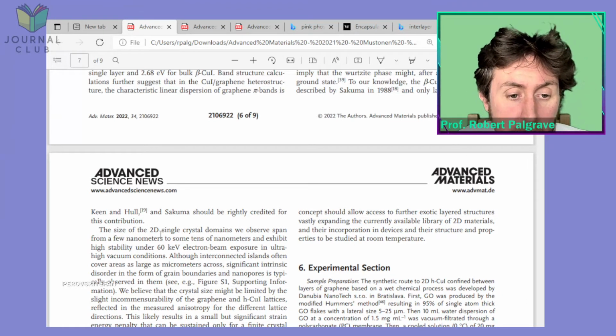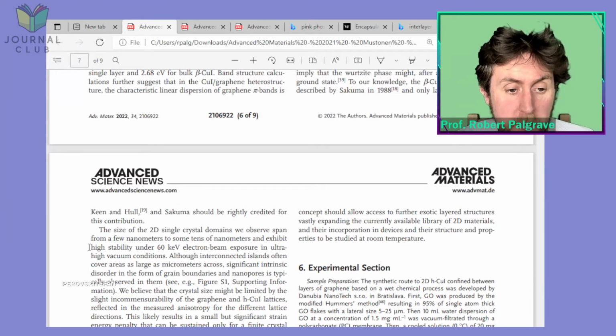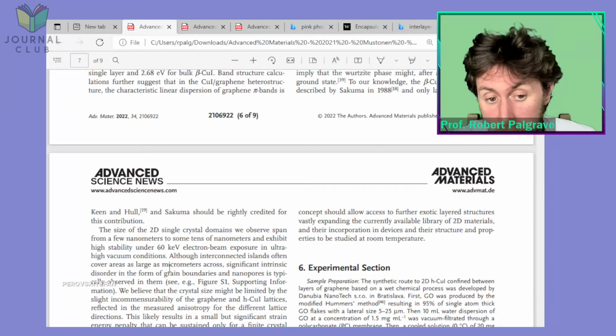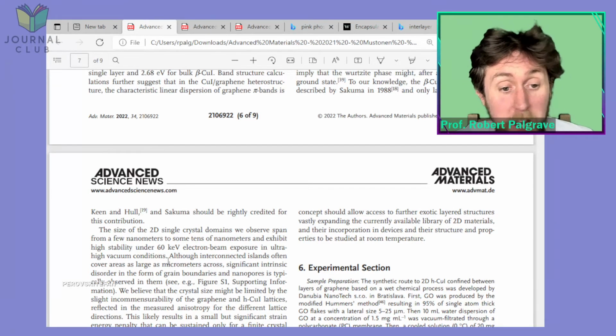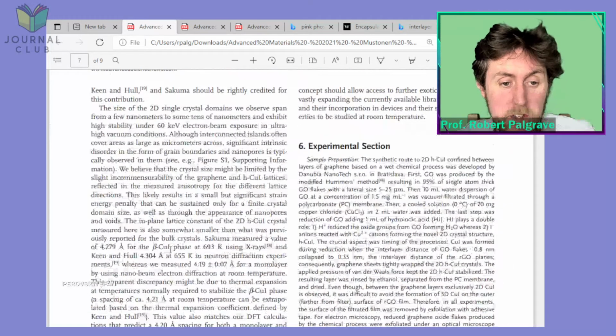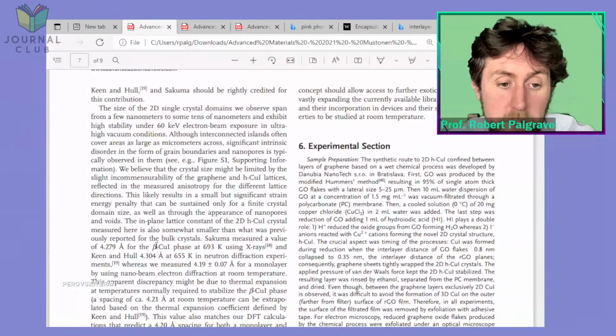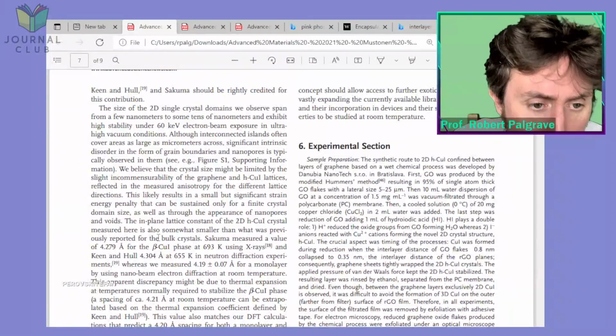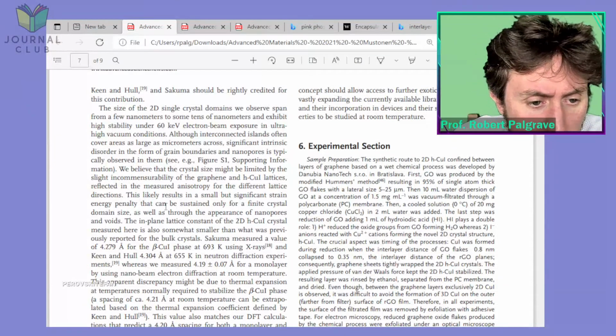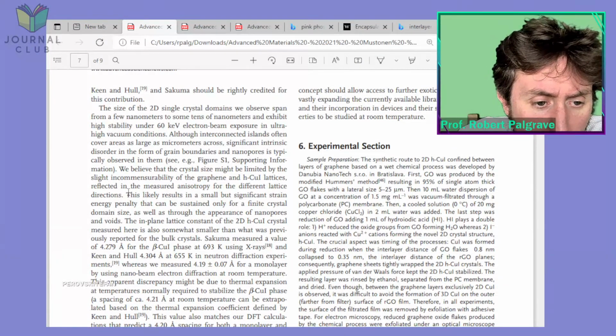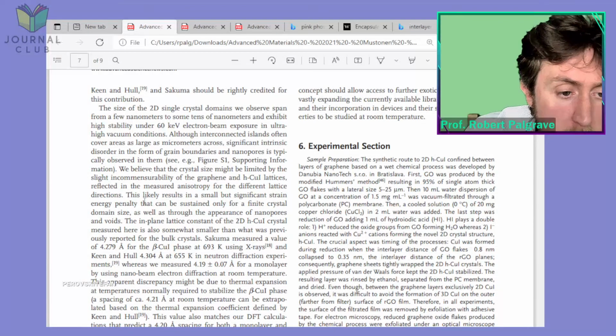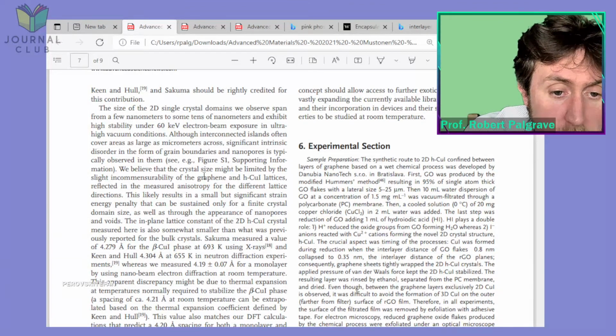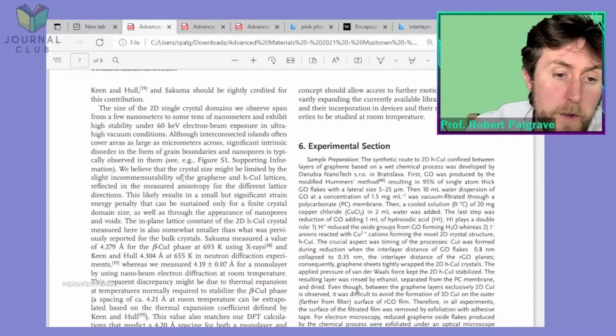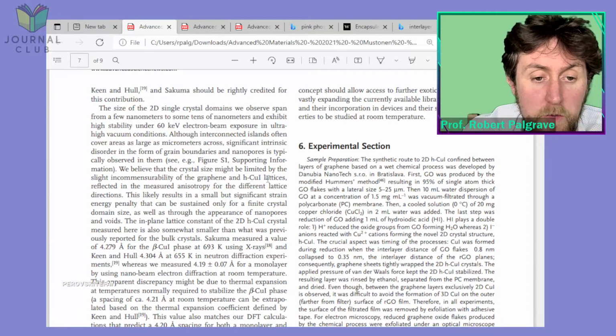The size of the 2D single crystal domains we observe spans from a few nanometers to some tens of nanometers, and they exhibit high stability under electron beam exposure and ultra high vacuum conditions. Okay, that's obviously useful for them because they were able to use the microscopy to image them. Okay, so yeah, let's talk about the actual structure then. We believe the crystal size might be limited by the slight incommensurability of the graphene and hexagonal cuprous iodide lattices.